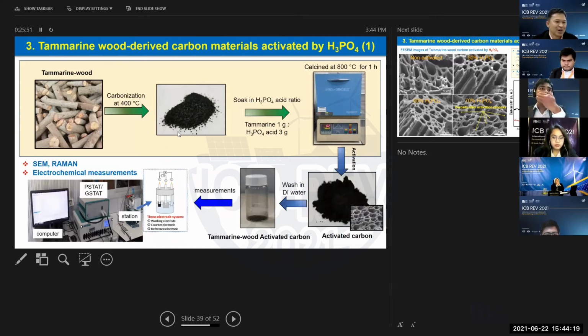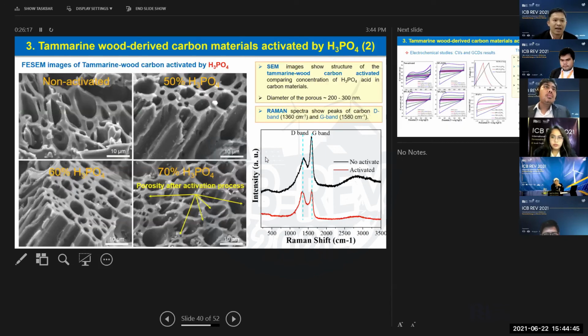Because in Thailand we also grow a lot of tamarind, so one of my postdocs wanted to try, so he prepared the tamarind wood derived carbon. Of course, we use the carbonization process, and we use phosphoric acid as the activating agent, and we also study the basic characterization as we have done before on the other materials. So for the Raman spectroscopy, this also confirmed the formation of carbon in the material prepared from tamarind wood.